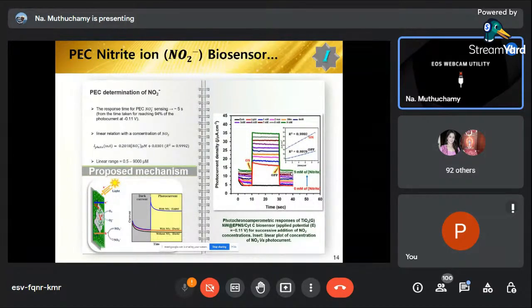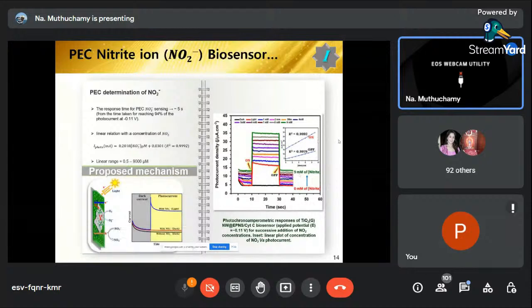So it shows good sensitivity and also excellent selectivity. Sorry, I didn't present that data. The selectivity didn't show any interfering response. It also shows a wide linear range, from 0.5 to 9 millimole. That means it shows wide linearity. Also, the limit of detection is very, very important. It shows a really good limit of detection, around 0.5 micromole.